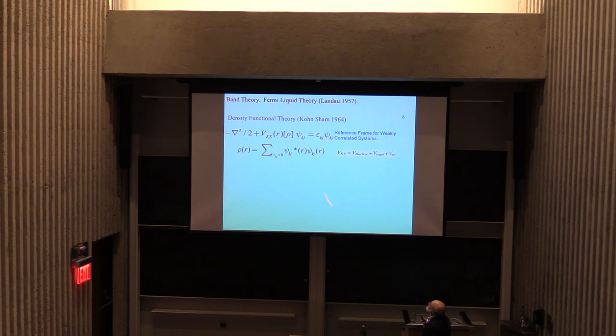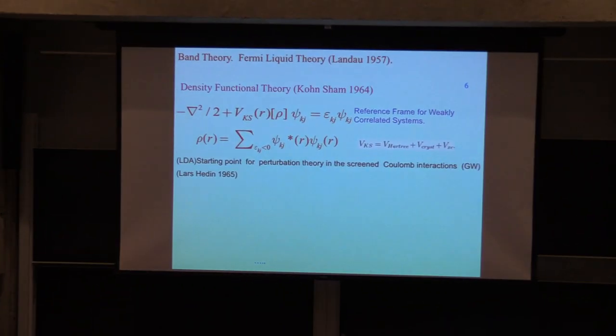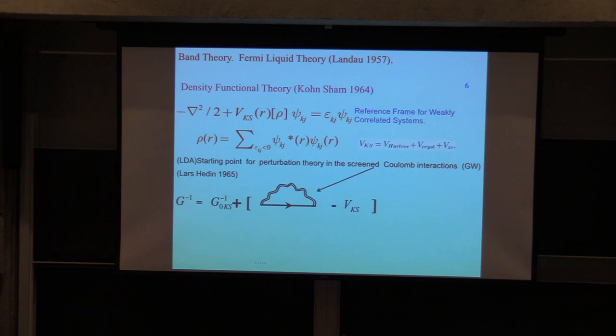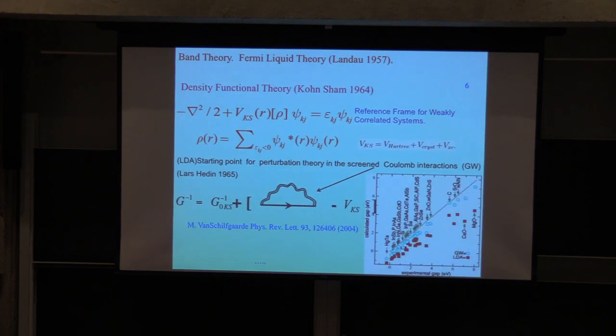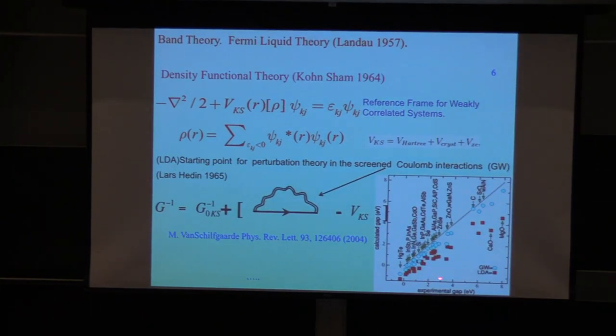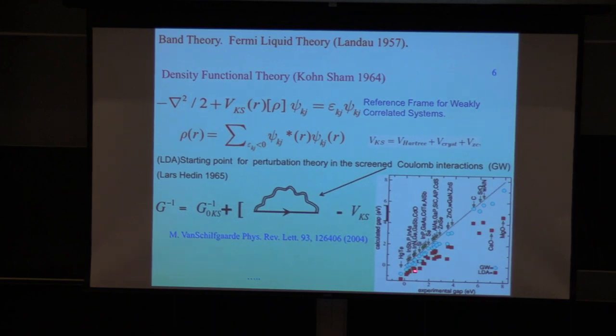And then by solving this reference system of one particle excitations, we get a good starting point for doing perturbation theory. In which sense? Well, we typically do just the first correction, which is the one interaction, one Feynman diagram in the screened Coulomb interaction, and that's really enough. This is called the GW method, and the reason why we believe that is because it's been tested, and here, for example, is a famous plot of many, many semiconducting materials. This is the gap, which is the energy that I need to excite an electron from the occupied states to unoccupied states. If one does the density functional theory, the gap is usually underestimated by some amount. When we put in the first perturbative correction, then we fall on the experimental plot more or less, and we get the right answer.